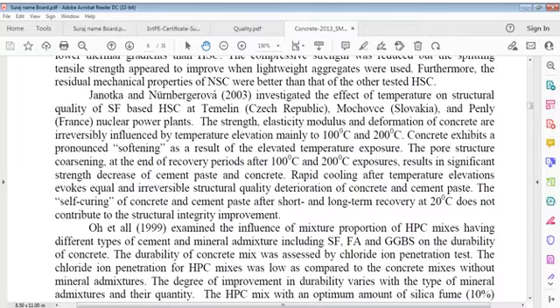Concrete exhibits a pronounced softening as a result of elevated temperature exposure. Pore structure coarsening at the end of the recovery period after 100 to 200 degrees Celsius exposures results in significant strength decrease of cement paste and concrete. Rapid cooling after temperature elevations evokes equal and irreversible structural quality deterioration of concrete and cement paste.